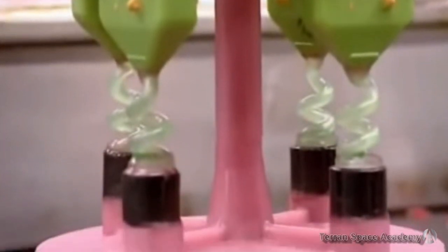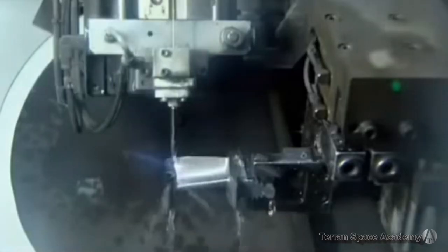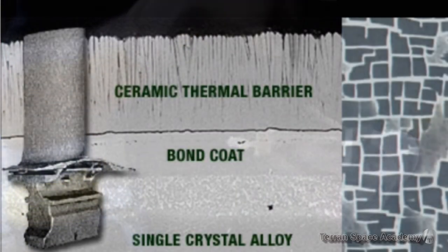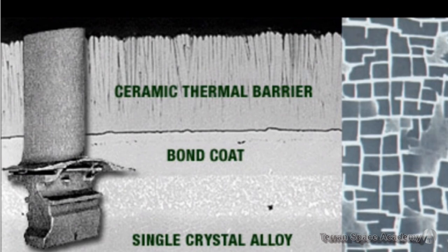The ceramic mold is then heated in a furnace and molten alloy is poured in through a helical structure to spin the molten alloy for even distribution. The mold is filled and the alloy hardens. The ceramic mold is dissolved in a caustic alkali solution. Holes for the cooling air are precisely drilled out with electrical discharge machining. Then electron beam physical vapor deposition is used to apply the insulating ceramic coating over the single crystal alloy blade.